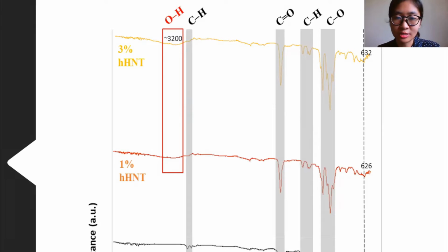A band shift was also observed for 1% and 3% PLA HHNT fiber composites at 626 and 632, which are associated with the formation of silicon-oxygen-aluminum bond stretch of halloysite. So these findings could be attributed to the bonding interactions between PLA and HHNTs.